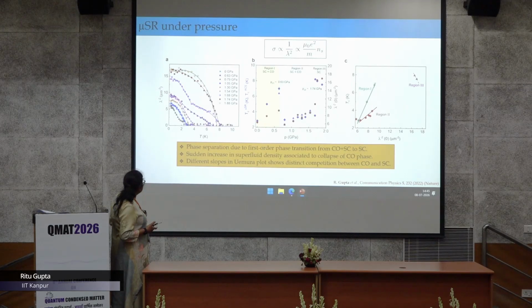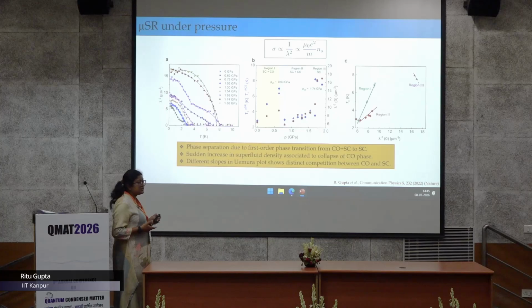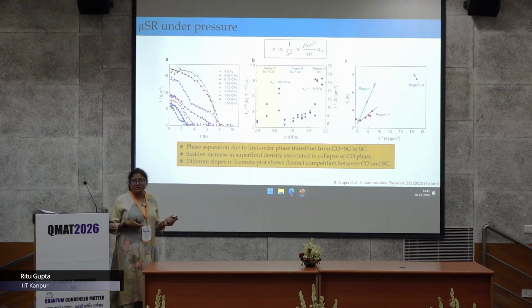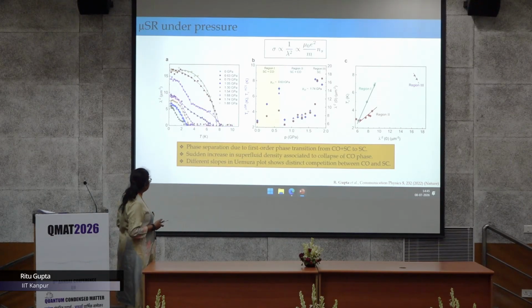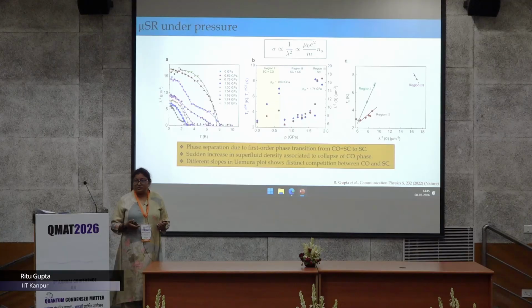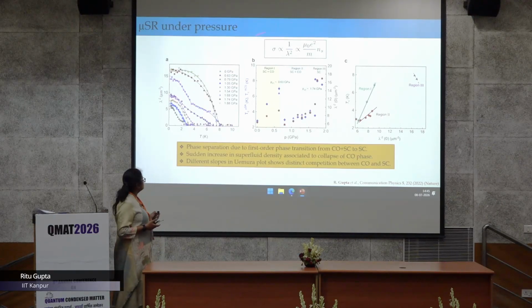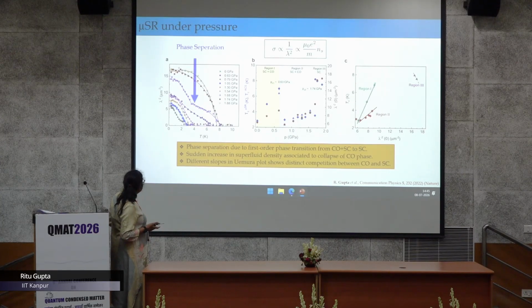And also, over the whole pressure range, the data could be fitted well with the multiband nature of superconductivity. That means superconductivity is not changing its nature. So something is there with the charge order phase. And one interesting feature we see is this double step like behavior here. And this pressure 1.68 GPa lies exactly between these two regions, region 2 and region 3.